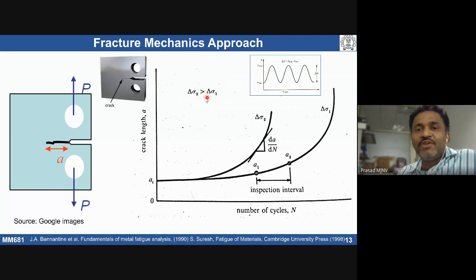Here, for example, I have given two different stress ranges. Assume delta sigma 2 is greater than delta sigma 1. It is obvious that if the stress amplitude or stress range is more, the number of cycles to failure is going to come down. Am I right? If the stress range is more, that is going to bring down the number of cycles to failure. So what people do is, at a given stress range, monitor how the crack is propagating with number of cycles. With increasing stress range, the number of cycles for propagation is going to come down because you are giving more stress, so the propagation will be faster.